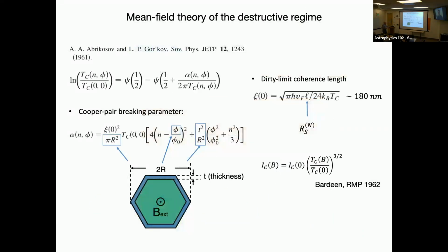In fact, the mathematics of understanding this dates back also to the 1960s. I won't belabor this except to say that it's straight up mean field theory of Abrikosov-Gor'kov, with only one adjustable parameter in the whole thing, which is the critical temperature at zero magnetic field, the zeroth lobe value, a number for aluminum, lead, niobium, or something. You have to put in some number that sets the overall scale, and everything else is determined. In fact, even this alpha, which is the parameter that controls superconductivity, is given by the diameter of the wire, the applied magnetic flux, the coherence length, which is in this case just dependent on the normal state resistance, and everything else is determined in here except this value of the critical temperature.